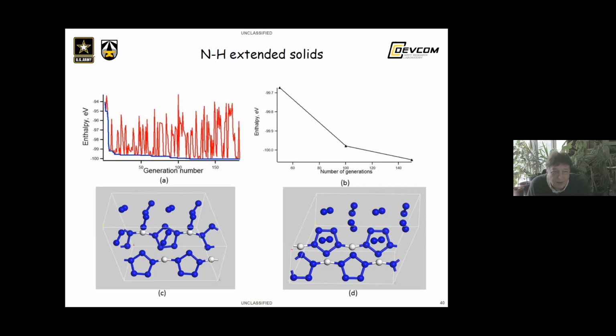Here we present the results of prediction of nitrogen-hydrogen structures at pressure up to 50 GPa. Here is the illustration of how long evolution changes the structure. So this structure obtained after 100 generations, and this structure obtained after 150 generations. Note rotation of the pentagons in the second layer.